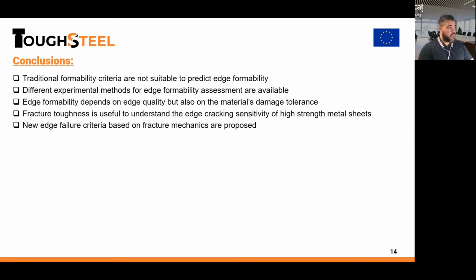And finally, to conclude my presentation, a summary of the conclusions. We have seen that traditional formability criteria are not suitable to predict edge formability. We have seen that there are different experimental methods for edge formability assessment, like the hole expansion ratio, hole tension test, or half specimen test or shear edge tensile test. Importantly, a key message is that edge formability depends not only on the material itself, but also on the edge quality. And finally, fracture toughness is a useful material property to understand edge cracking sensitivity of high-strength metal sheets. According to these experimental observations, we propose a new fracture criterion based on thickness strain or fracture strains measured in pre-crack specimens.